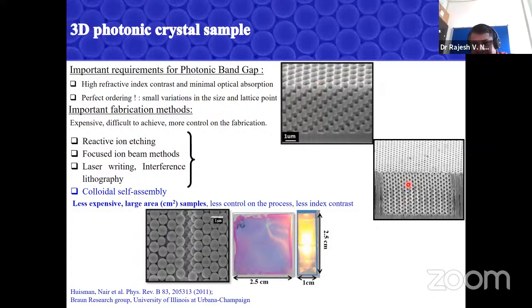And this is another system which has been one of the champion structures giving these photonic band gap features, where you can again see that you take a piece of silicon, you etch first from the top direction and second from the cross-section directions. So you get a kind of network structure, but these are nice periodic structures. And the third structure, which is quite popular, probably 70% of the community use it because it's easy to make and not that expensive, is called the self-assembled system. We are also going to talk about these kinds of structures quite a lot in this talk.